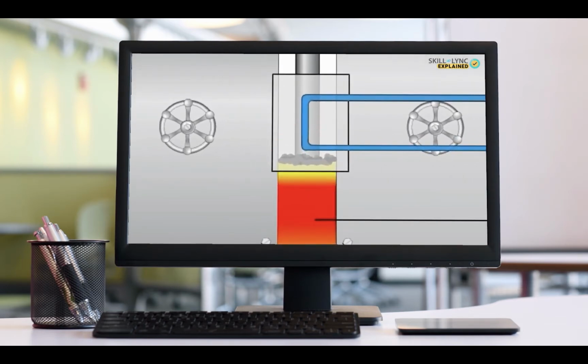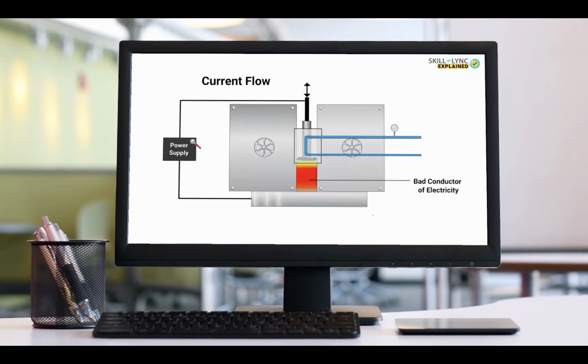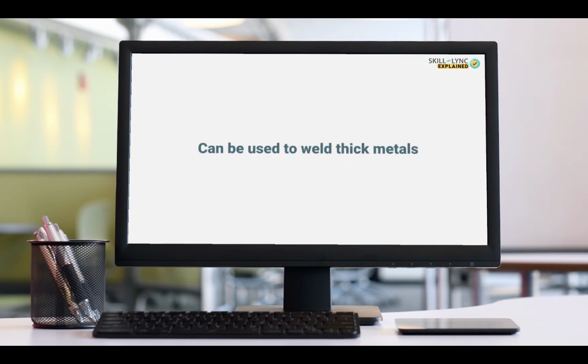the weld pool. This aids in continuous generation of heat as well as protection of the weld pool from oxygen and other atmospheric elements. While welding very thick materials, the holding die is moved along with the weld pool as it increases in size. Since most of the metal at the bottom would have solidified, this wouldn't be a problem. The electrode feed can also be increased by adding more than one electrode wire into the joint. Due to this specific reason, thick metals can be welded together quite easily with electro-slag welding.